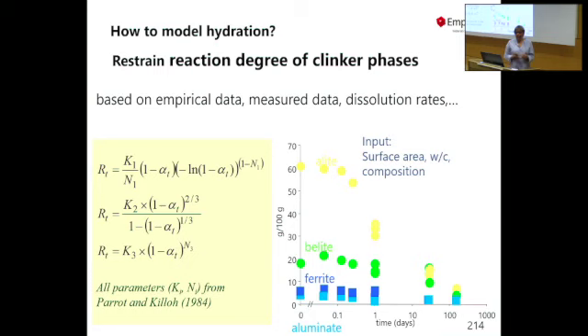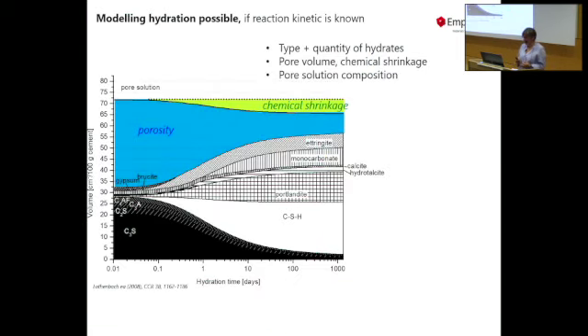The clinkers, they do not react fast, they react over days, weeks, months. And so we looked in literature and found a very simple equation from a paper from 1984, which just needs the surface composition, the surface area, the water-cement ratio, and the amount of clinkers, and gives you a reasonable hydration speed, which agrees well with what you see by XRD. Then we put that into our software, and if we restrain the clinker reaction, we can then start also to predict the hydration of a Portland cement, as you see here.